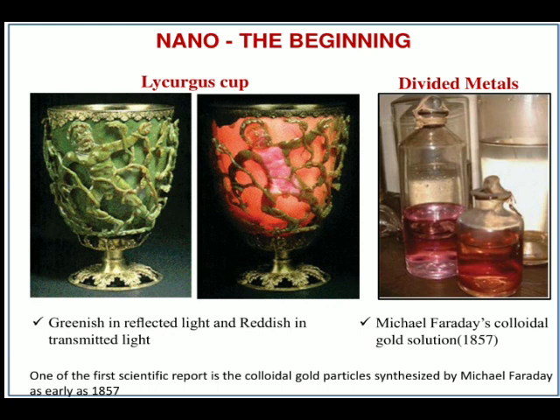66.2% silver, 31.2% gold and 2.6% copper in a glass matrix. The red color is observed as a result of absorption of light by the gold particles, and the purple results from the absorption by larger particles, while the green color is observed due to light scattering by colloidal dispersion of silver particles within the size of 40 nanometer. And the Lycurgus cup is recognized as one of the oldest synthetic nanocomposites.